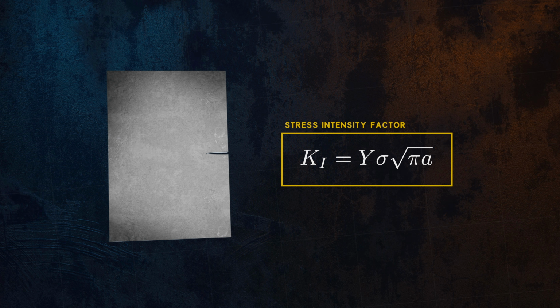For an edge crack in a large plate, Y is around 1.12. This crack can open more easily, which makes it more severe than an equivalent crack in the interior of the plate. For an edge crack, a is the full length of the crack, not the half length.